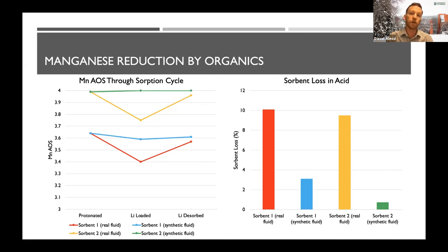And that's exactly why, you recall a few slides ago, we saw that relatively high manganese concentration in this lithium concentrate in the acid. So what this means is every time you do this, you're burning up some of your manganese by reducing it. It goes back into the acid and you're losing that manganese every single cycle. This is called the process of reductive dissolution in geochemistry, and it's problematic. We want to minimize this. What you see in the green line here is a synthetic brine, right? No organics. And it just is not happening there. The sorbent is super stable there, and that's the one where we were getting well under a 1% loss, okay?